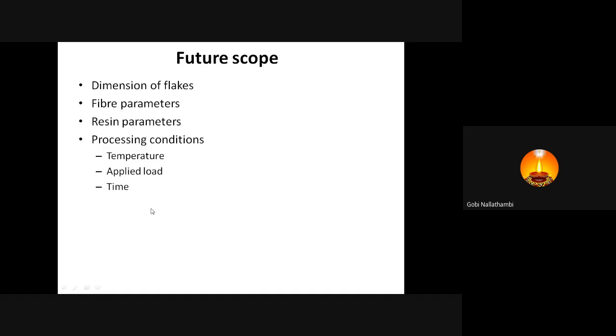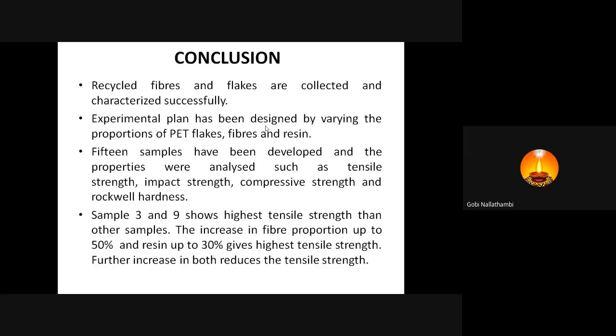Then we can vary the process conditions like the curing temperature, the applied load, where 120 kg per square centimeter is applied in our process, but we can change this, and also the time required to cure the sample. These 3 we maintained as constant during our process, but we can also analyze the effect of these 3 on the various properties of the composite. This can be done, and we can also optimize various parameters. We can then arrive at very suitable and excellent composites from recycled materials.